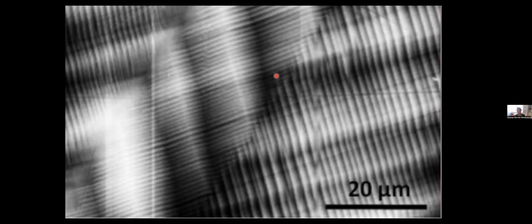So what I mean is, here's a microstructure of a nickel manganese gallium alloy, which forms a finely twinned martensite-like microstructure, except for the fact that this material is magnetized. So every time it forms this interface, it does not only have to satisfy minimum elastic energy conditions, but also needs to ensure that each of these variants that are magnetized satisfy a divergence-free condition so that they're not trapping certain magnetic monopoles inside the body. Magnetic monopoles, for example, are very high energy states and are only observed in a theoretical framework. And so you need to ensure that your magnetization flows smoothly around this interface and does not break any of the divergence-free conditions.